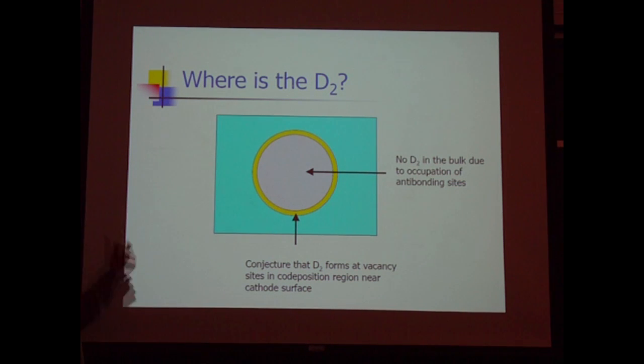So the big picture that we're evolving to in the Fleischmann and Pons experiment: what is the experiment actually doing that's useful and helpful? You start out with palladium, load up with deuterium, but the internal region, from the arguments I've given, is inert. It doesn't do anything at all. It's just sitting there. On the other hand, you get co-deposition of palladium on the surface, and if you do that when the loading is very high, it makes lots and lots of vacancies. Those vacancies can host D2 on the surface. And according to me, that's what the Fleischmann and Pons experiment is actually doing in terms of constructing a region where something new and something interesting has the potential of happening.